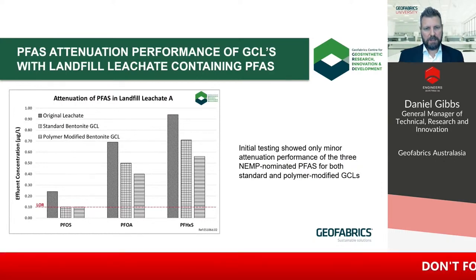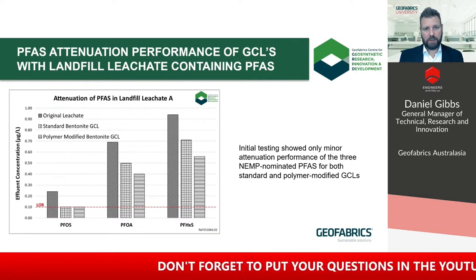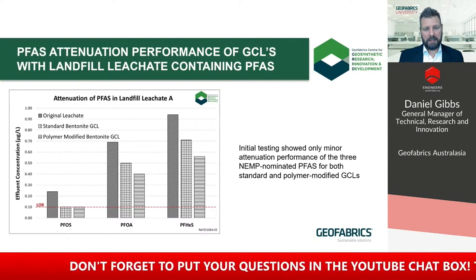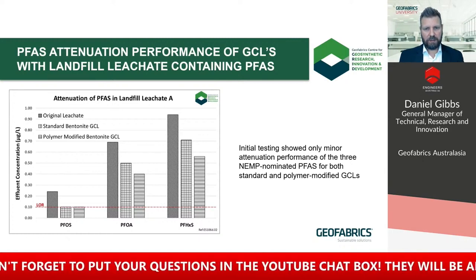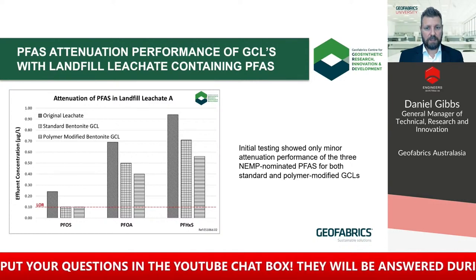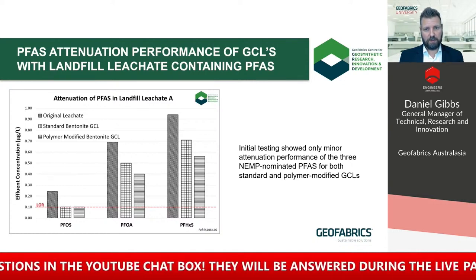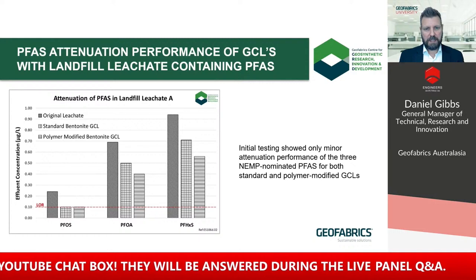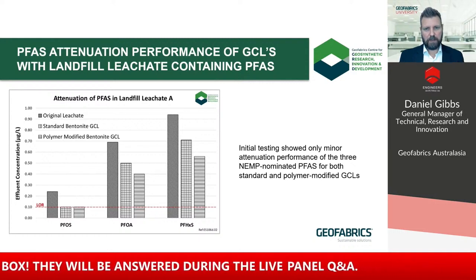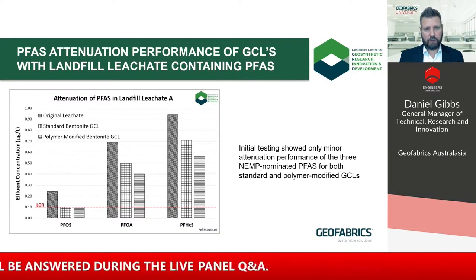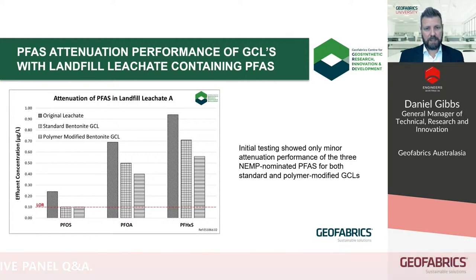In some of our early research studies, we quickly discovered that the bentonite core, while it generally has a reputation for reducing contaminant transport due to its low permeability, couldn't trap these three specific long-chain PFAS molecules very well in either standard or modified forms. Some of the uptake you see in these graphs, particularly for PFOA, could be linked to sorption onto the polypropylene synthetic components. We're investigating this further in a cooperative study with Monash Uni at the moment, so this could be included in a future webinar.